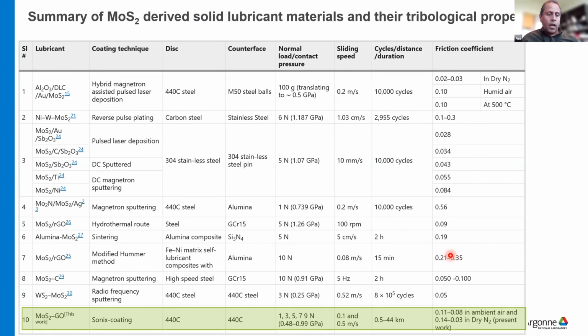So over the years, people have been combining MoS2 with other materials, like oxides mostly. And these are all thin films. But in this case, we came up with using 2D materials, because we don't need to go into the vacuum and then all the CVD or PVD processes to produce this kind of coating. We just produce this 2D material, spray coat it, and then it can be done in atmosphere. So that's where I think the first thing is to reduce the cost completely, a very easy process, and even for 3-dimensional material. And here, for the first time, we show that the durability is much better than any other thin film coating that has been shown before.